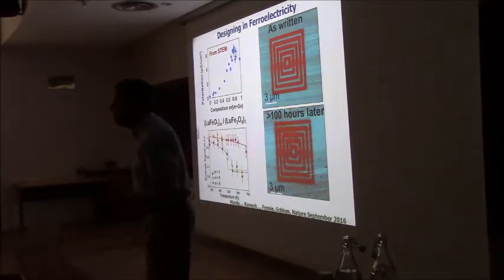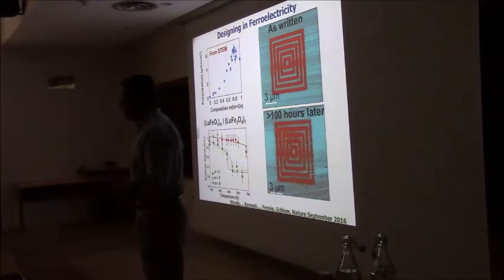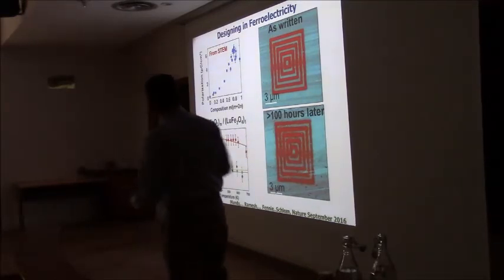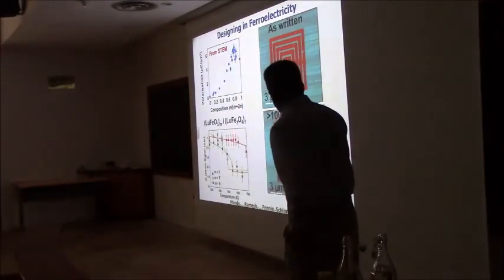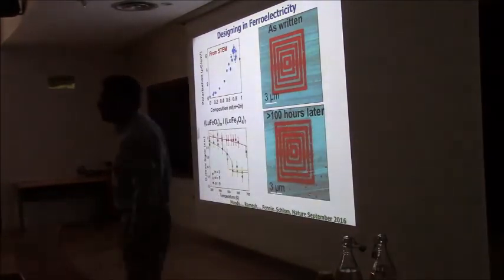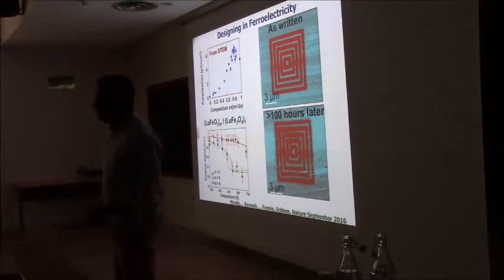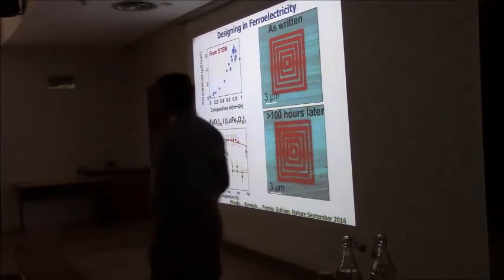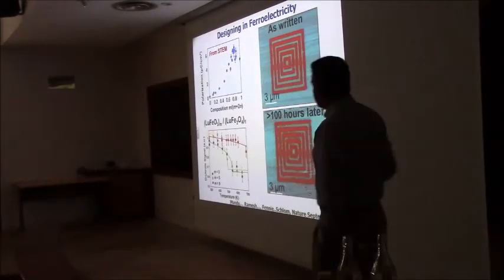And this took us a while because we don't have bottom electrodes yet. We just got those electrodes done. So we had to remove the substrate, put contacts, etc. Those are very stable. This is after about 4 days, 5 days worth of testing. You can see those patterns still are stable. We have now checked them several months after writing them. They're still very stable. So it doesn't look like these are just surface charge modulation. It is indeed switching the piezoelectricity.